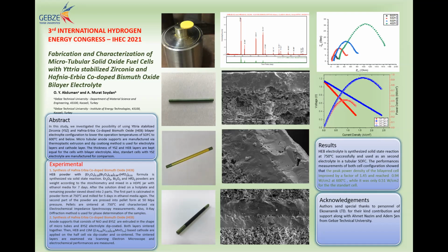First, we extrude anode supports in tubular shape, then coat them with YSZ electrolyte, and then co-sintered the samples. You can see the micrograph also on the central block of the figures, on the second one, just below the XRD results. And then we coated the HEB layer via dip coating also.